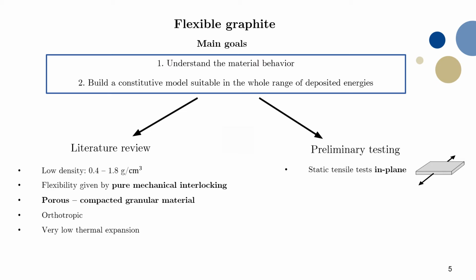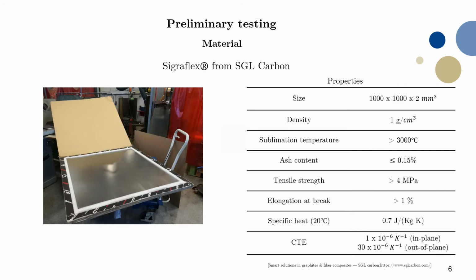In order to understand and have a global look at the material from a macroscopic point of view, we set up static tensile tests in the in-plane direction. The material chosen is Sigraflex from SGL Carbon, and here in the picture it is shown as delivered, in the shape of very thin foils, 2 millimeters of thickness, and its tensile strength is very low. It can exceed 4 megapascals, and also the elongation at break can exceed 1%.